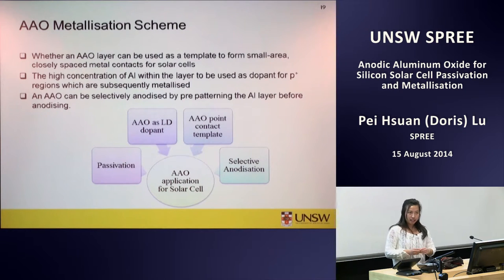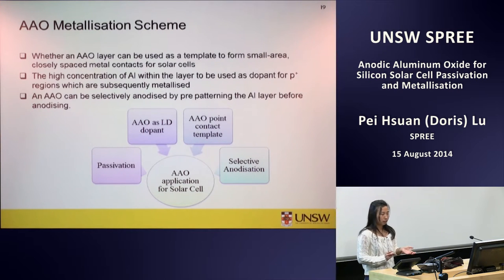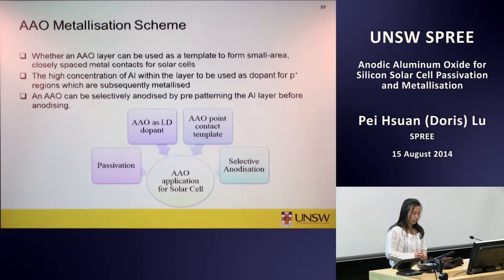So with the AAO template, it could help to form the localized contact with its porous structure. And the high concentration of aluminium within the AAO layer could provide a doping source for laser doping, for example. The way to form AAO, anodic aluminium oxide, allows it to be prepared to form a conductive region and passivation layer by one metal deposition. And this process, I call it selective anodization.